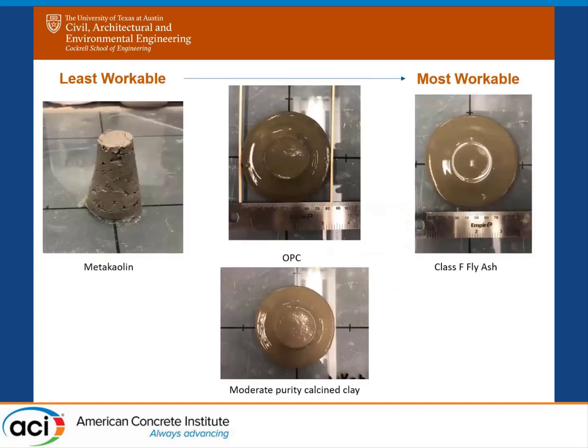So just a little bit more visual. The metakaolin was on the left, and this wasn't quite a valid test because I actually had to scoop it into the actual slump cone. And then we have OPC in the middle. And again, this is a 0.5 water cement ratio and the moderate purity calcined clay. So that was the 65% kaolinite, just like the true moderate one. And those were very similar. And then your most workable, the class F fly ash.